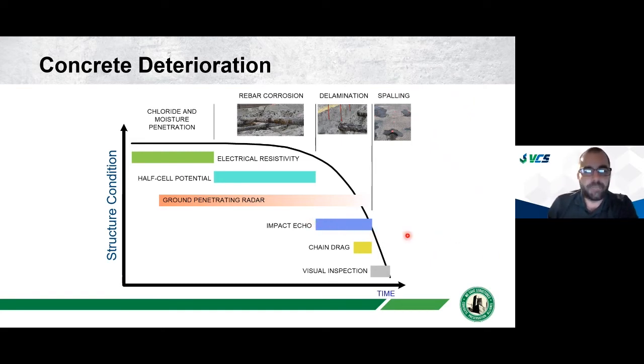We can use things like impact echo, which will identify the broader range of delaminations much earlier than hammer sounding or chain drag. GPR is a very versatile tool that identifies a lot of different condition states. Corrosion potential half cell can identify active corrosion. Concrete resistivity is affected by chloride and moisture content. As I go through some projects here, we'll talk about these methods and how they're used.